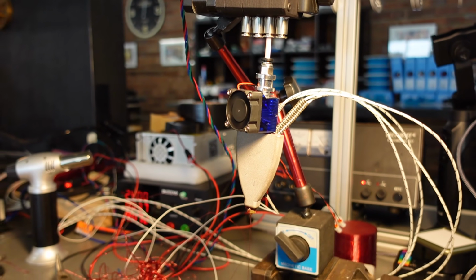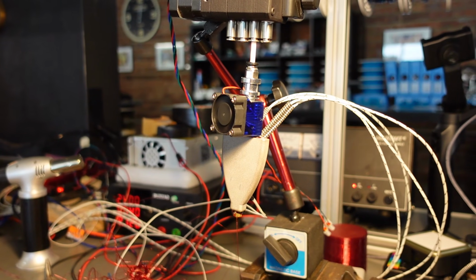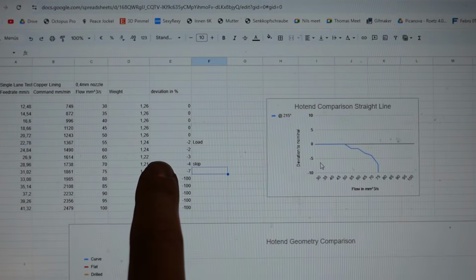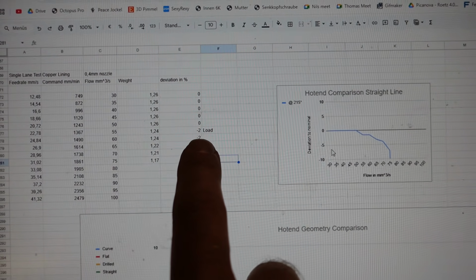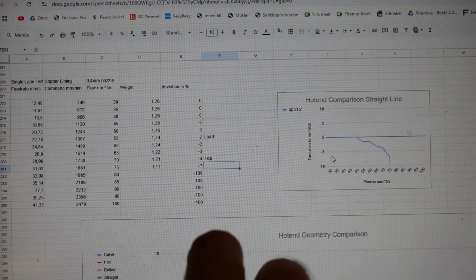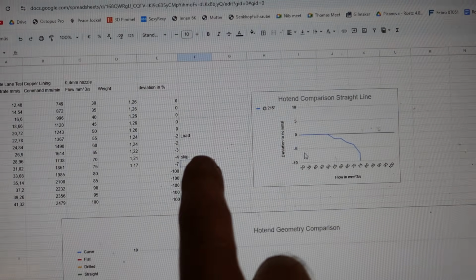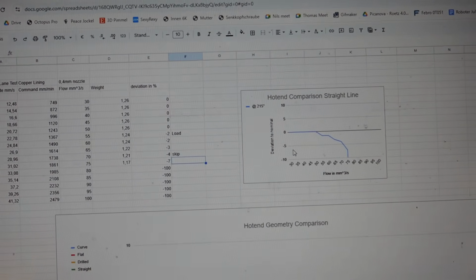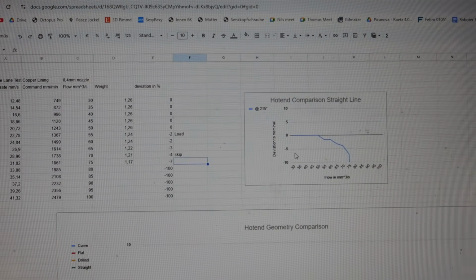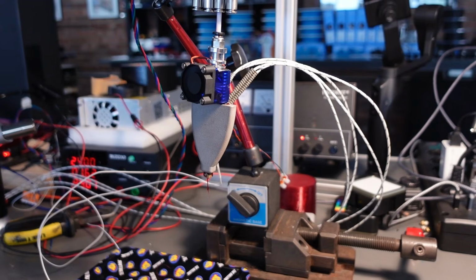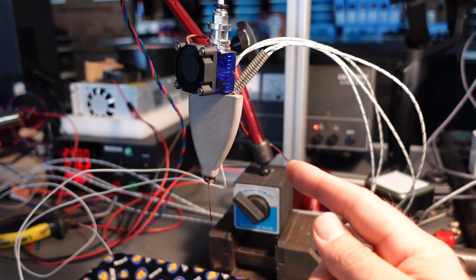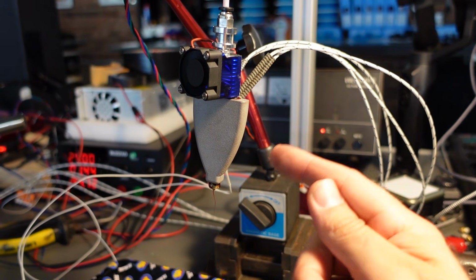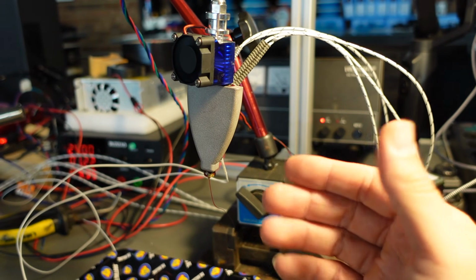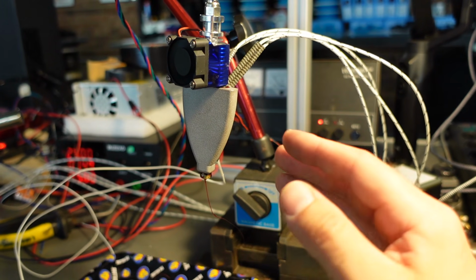I would have guessed these numbers are higher, but we'll investigate why that is not the case. So you can see it started to taper off around 55, and I could see a visible difference in the viscosity of the material at that point, and then it skipped hard at 70 and 75 cubic millimeters. So it is basically on the low performing end of everything we have done so far. So usually physics is telling us what to do, and usually this copper material should have almost double the heat transfer to the filament, so why isn't it doing that?